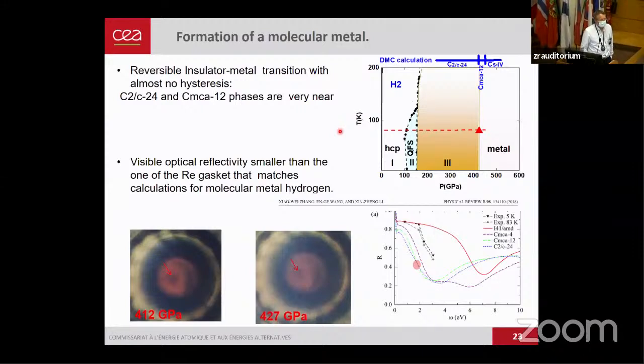Okay, thank you. I'd like to ask a question of my own. There are many possible mechanisms for insulator to metal transition: a pure band structure effect, as was suggested by Marvin Cohen, or it could be a type of Mott transition. So besides the very existence of the transition, what kind of experimental evidence can we have to attribute it to a given mechanism or another one? I think the essential measurement now will be to measure the structure, to really be sure that it's the C2/c structure up to that phase. Then it will validate the calculations or not. If not, we'll do other band structure calculations.